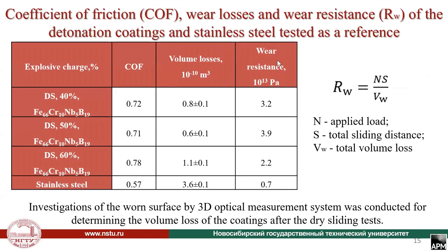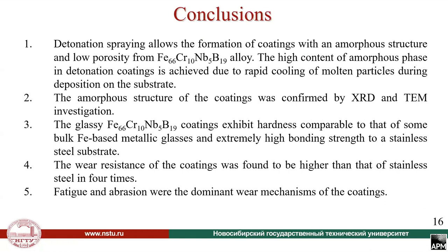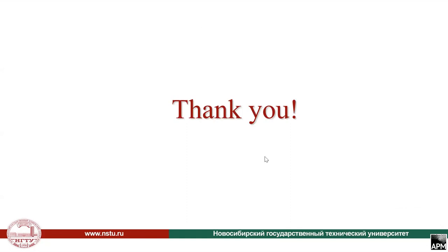Here is presented the wear resistance, which was calculated by this equation, which shows that the wear resistance of detonation coatings, which were produced in really wide detonation modes, is at least four times higher in comparison with stainless steel. And here is presented a conclusion for this work. This reported study was funded by RFBR and the Novosibirsk region according to a research project with this number. Thank you for your attention. I would like to answer questions if you have any.